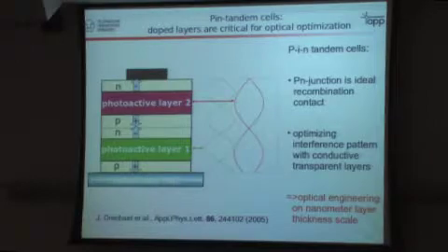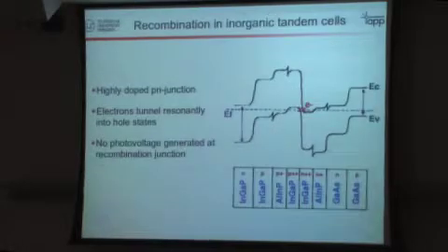Fortunately, a couple of years ago, we published a paper where we do this so-called PIN structure. These P and N layers are high bandgap transparent doped layers. First of all, they form a PN junction, which is a very good recombination contact. And secondly, you can vary the thickness of these window layers beautifully, and you can really adjust that. This was a key point. And fortunately, we also filed this as a patent, and that is one of the key IPs Heliatek has.